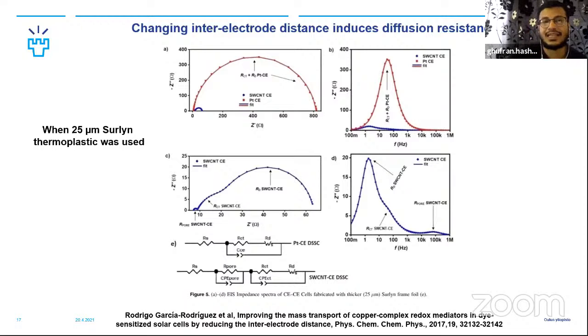And then another semicircle appears. For example, here there is no photoelectrode made, so there should be no third semicircle, right? But here you are still observing three semicircles. Why is that? It's because the carbon counter electrode exhibits these three. And this diffusion resistance, as I showed you, by just changing the inter-electrode distance with the thermoplastic from 10 micrometer to 25 micron, you can see a large diffusion resistance was induced. So with this electrochemical characterization, you can see how to minimize it, and that is affecting not only the open circuit voltage but also the fill factor of the cell. I see.